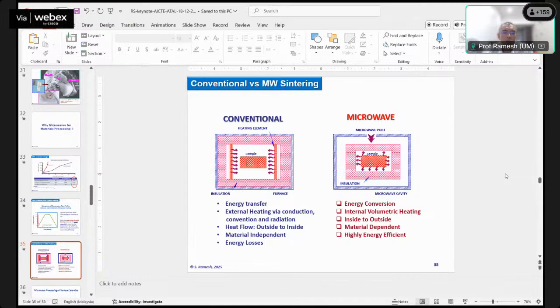Of course, we need the material to be able to couple microwave. This is the challenge when we want to microwave ceramics, because not all ceramics are able to couple microwave at low temperature, at room temperature. They couple very well when they reach a certain temperature, most of the time above 200 degrees centigrade. So sometimes we use susceptors to heat up the area. We use susceptors like silicon carbide.